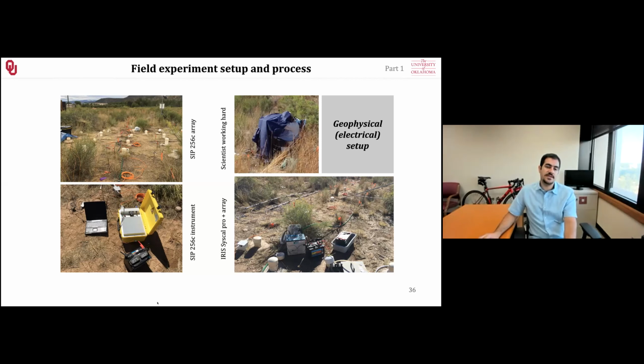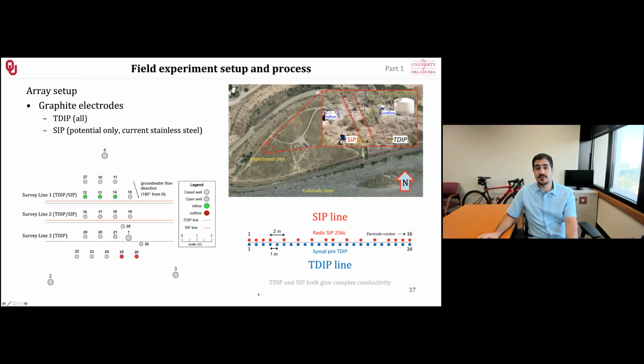Now, why we used only 2 lines for the SIP is because lower frequency measurements take forever. If you go to frequencies below 0.1, it can take up to 40 minutes and more for just a single frequency measurement. So we don't have that luxury in the field, right? We went all the way to 0.156, and that took us, for the whole measurement from 0.156 to 500 hertz, about 4 hours.